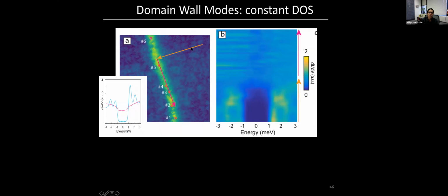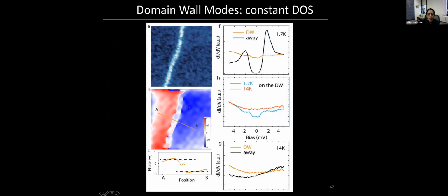So here is more data. This is a line cut, which goes this way and then this way. When you go in this direction, you see the nice superconducting gap, meaning the density of states is suppressed. And when you go along the domain wall, you see very featureless density of states inside the superconducting gap. Then you can actually increase temperature and make sure that this feature is associated with superconductivity. So this is the spectrum on the domain wall showing the finite density of states. And if you go to high temperatures, which is 14 Kelvin above TC, this entire feature disappears.